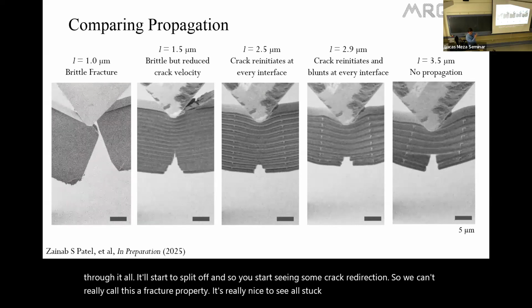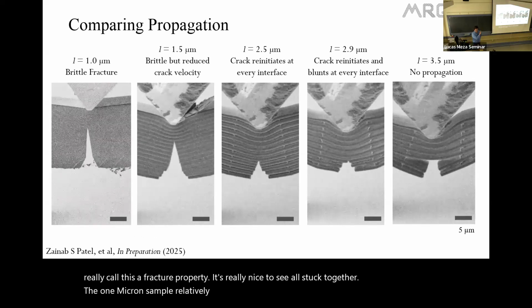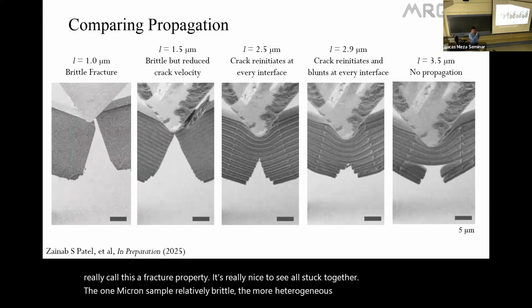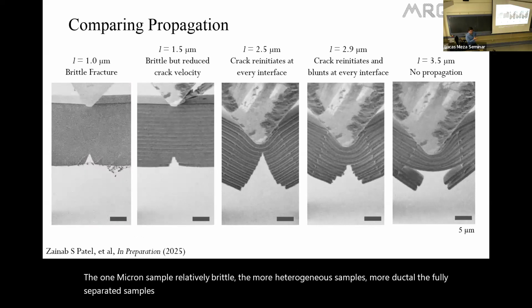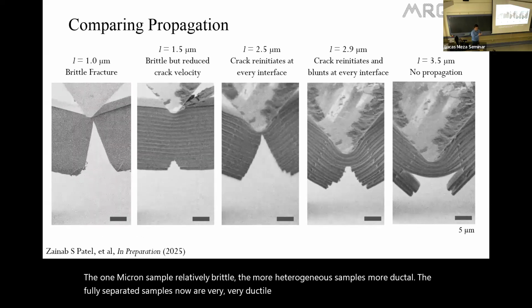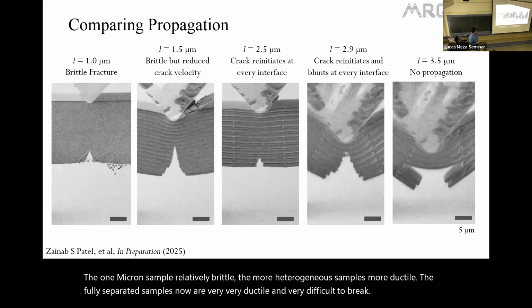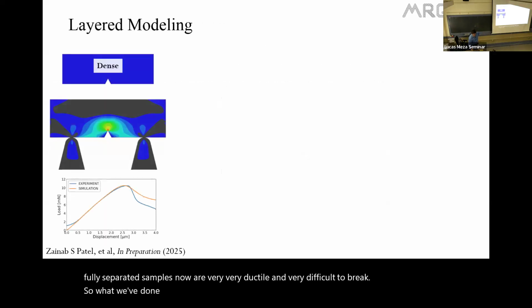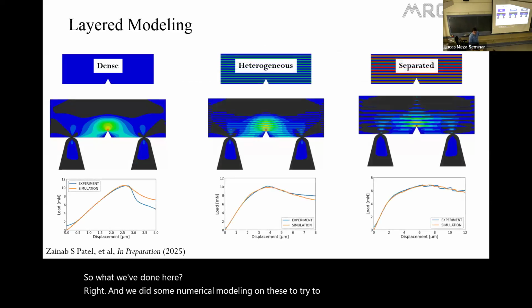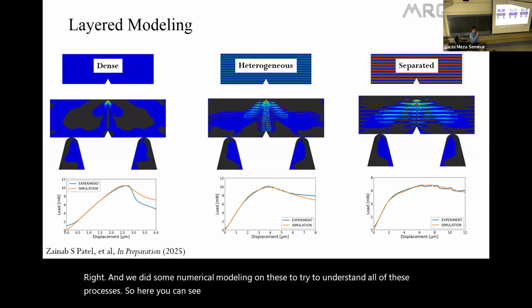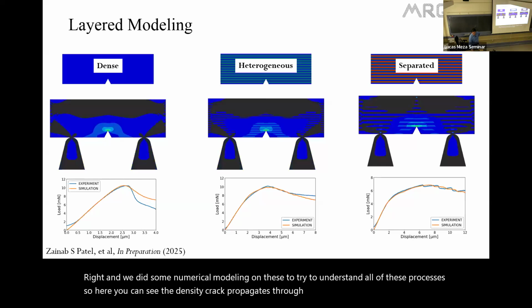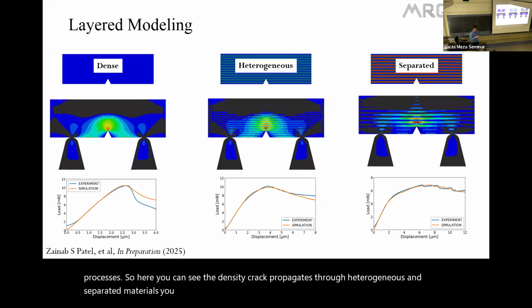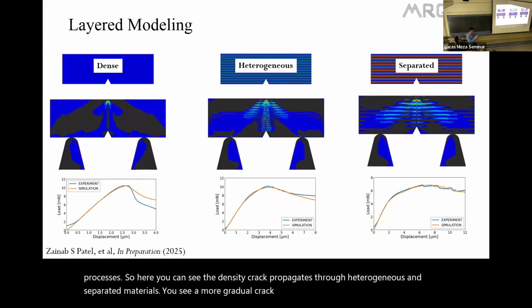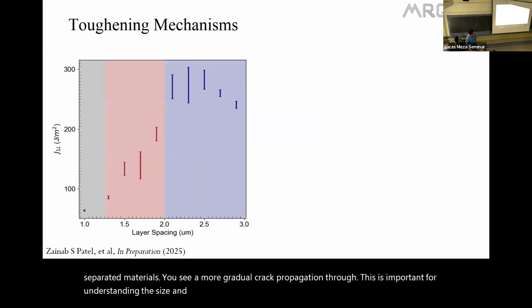The 1 micron sample, relatively brittle. The more heterogeneous sample is more ductile. The fully separated samples now are very, very ductile and very difficult to break. So what we've done here, we did some numerical modeling on these to try to understand all of these processes. So here you can see the dense sample, crack propagates through, heterogeneous and separated materials. You see a more gradual crack propagation through. This is important for understanding the size and extent of the plastic zone.